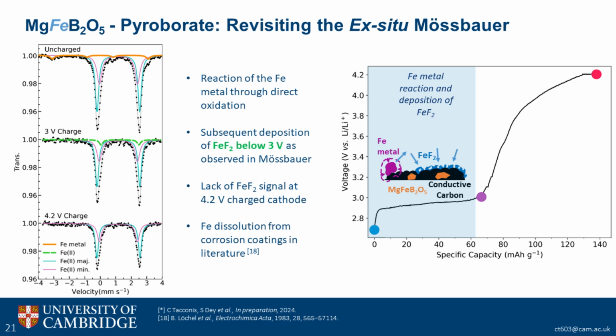So there's a lack of this iron fluoride signal at the 4.2 V charge, and this is further consistent with other reports of corrosion currents that show that the corrosion coatings, when you raise the voltage even higher, start dissolving off iron species from the surface. So in conclusion, what we think is the mechanism that's going on is highlighted in this figure here, and it's consistent with the whole suite of post-cycling analysis techniques that we applied to this material.